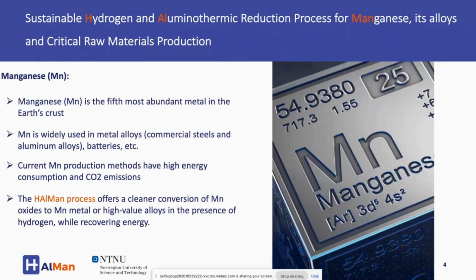And what we do in the HAlMan, we introduce a new process that offers a cleaner conversion of manganese oxide to manganese metal and also higher value alloys. And that is done by using hydrogen, and we do recovery of energy also for the process. Next slide, please.